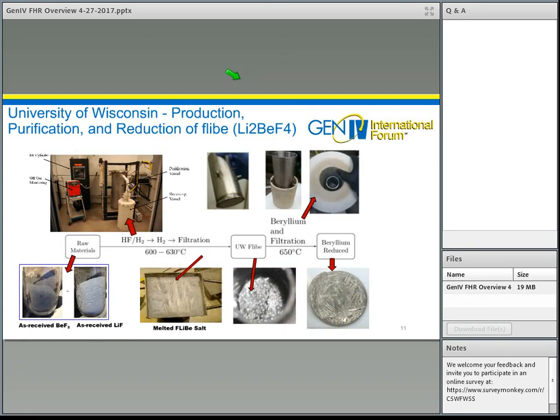At the University of Wisconsin, the capability to work with and purify and then perform corrosion testing with the Flibe salt has been reestablished. The motivation for using this type of salt, which involves the use of enriched lithium and beryllium fluoride, comes from the very low parasitic neutron capture and the high moderating power that this combination of salts provides. One always needs to use at least 2 salts to achieve a sufficiently low melting temperature to be practical. And this is the unique combination that has sufficiently low parasitic neutron capture and high moderating power that one can design cores that have negative coolant void and temperature reactivity feedback.